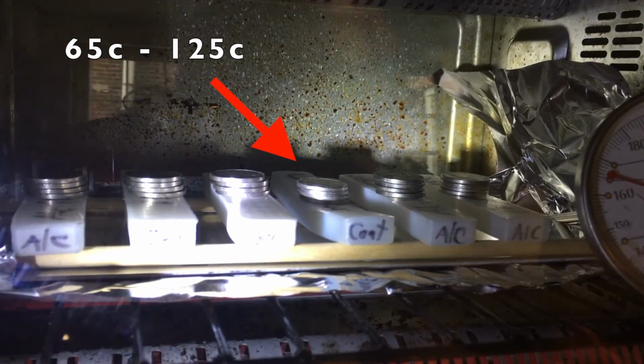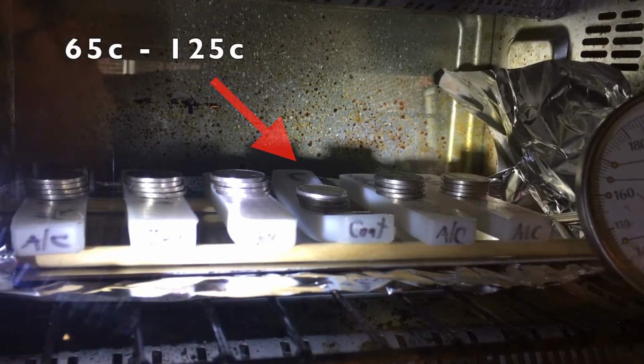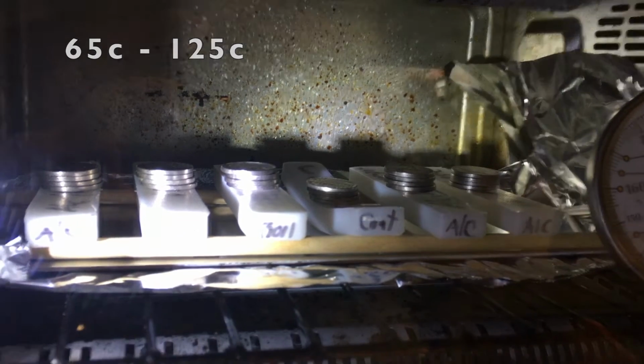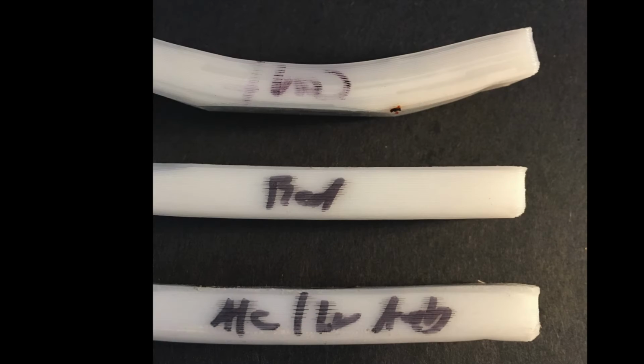The control starts melting immediately, and then basically all of the other treatments were effective to one degree or another. As far as heat deflection goes, cooking it on the bed seems pretty good in this situation, but these are pretty much the ideal conditions for doing that. A very flat, evenly dimensioned object without a whole lot of details is going to do very well cooking on the bed. And you can see the alcohol at ambient has a little bit more movement, and the control up on the top was pretty much rainbow shaped at this point in time.